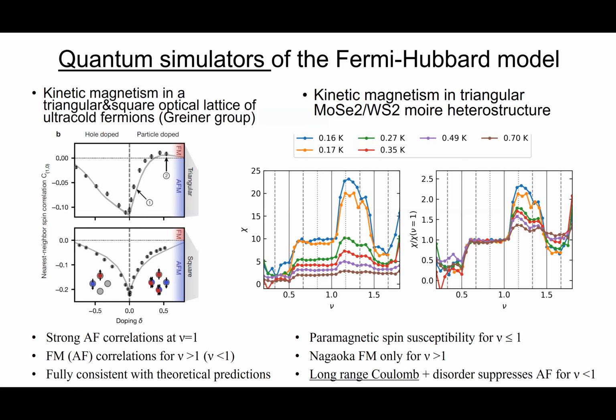So it seems like it's working in another material system, which is very rich, the molybdenum ditelluride tungsten diselenide. So there, again, this band tuning leads to two very interesting effects. One of them is in one regime, when the energy difference is sizable but finite, you can indeed have itinerant electrons in very dispersive tungsten bands. And there are indications of heavy fermion physics. And when they bring it together, then the bands hybridize and you obtain Chern bands.